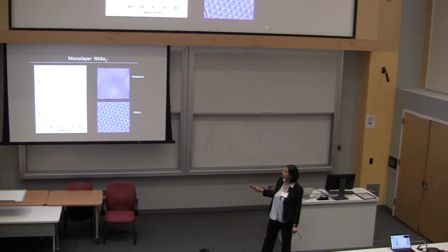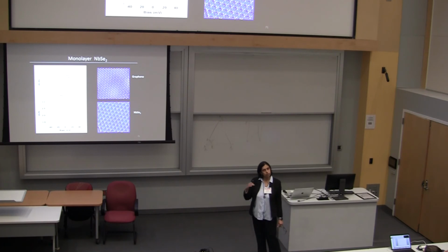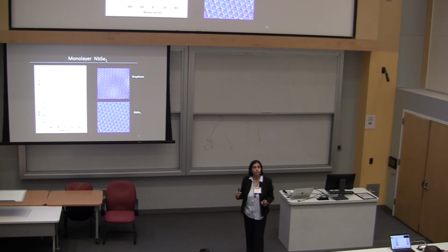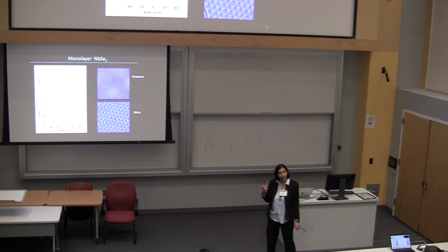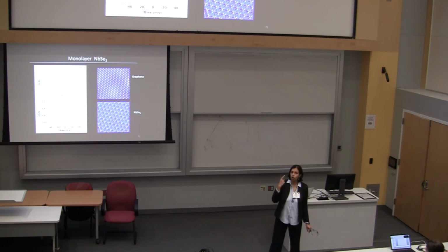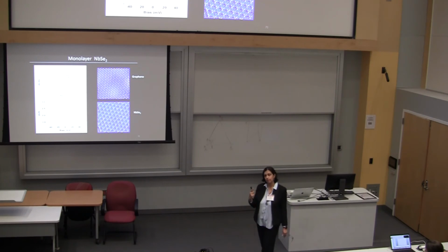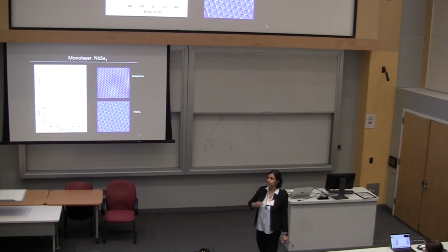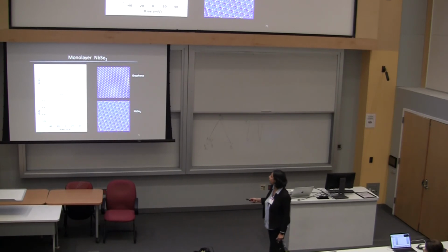Interestingly, niobium diselenide in the bulk is a metal, but this looks like a semiconductor. As it turns out, when you thin the material down to the monolayer limit, a lot of the bands are pushed away from the Fermi energy, and there's only one band that actually crosses the Fermi energy. And that's another reason we were interested in this system, because it turns into a one-band superconductor, which we might be able to tune into different regimes simply using gating.